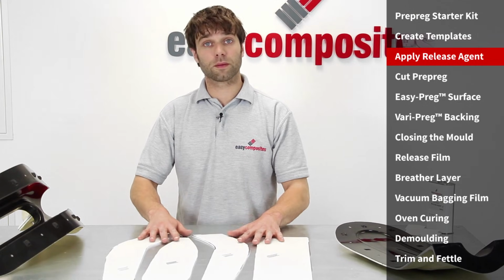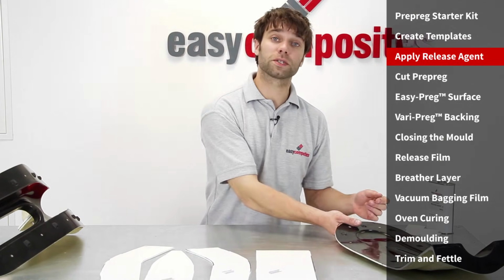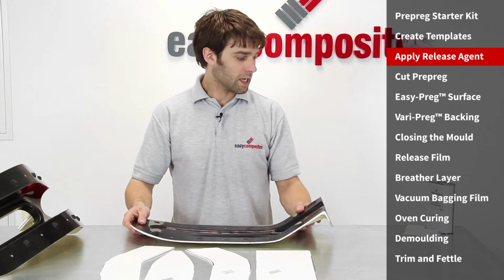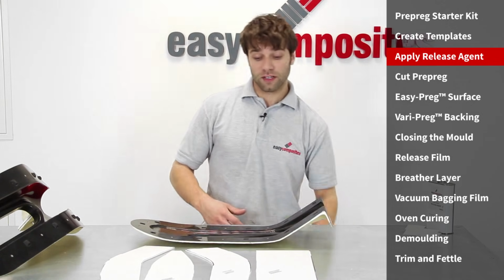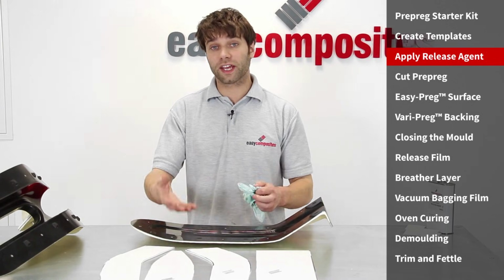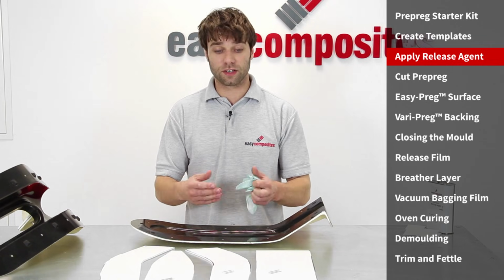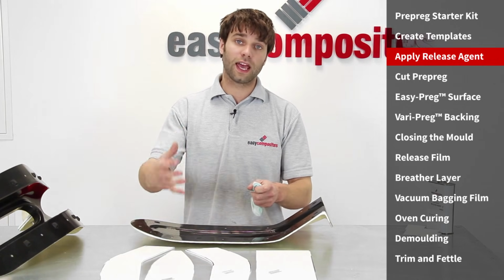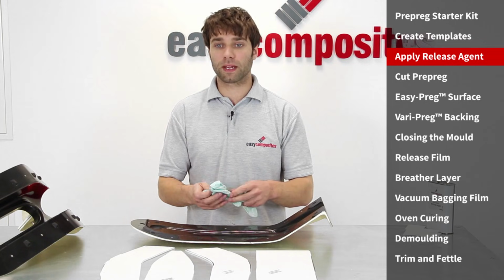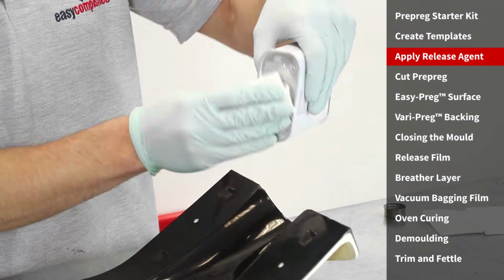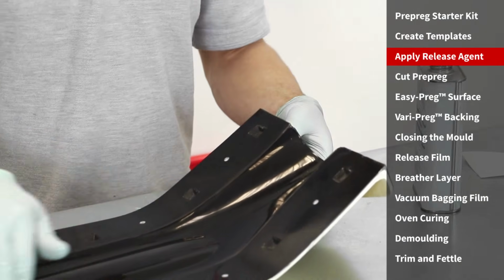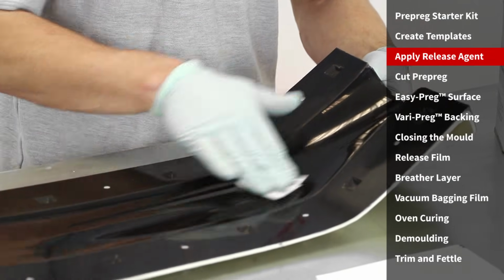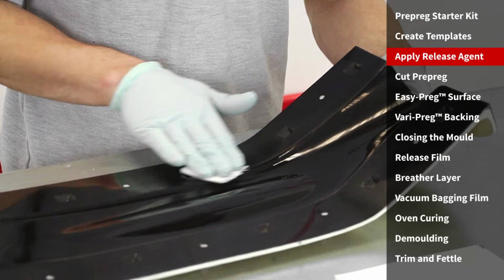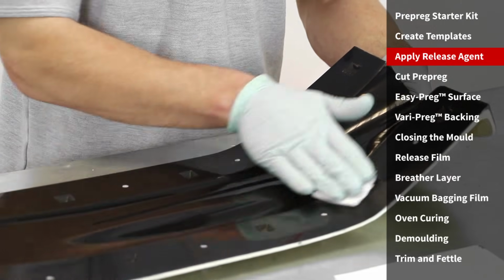Before we go on to cutting out the pre-preg material itself, we're going to take the opportunity to apply release agent to the mould. Now, as you may have already gathered, we've produced a part from this, so it's already had several applications of release agent, but it's always a good idea between every release to apply one more application. Conventional release agents such as wax and PVA don't work for pre-pregs because of the high temperatures that are involved, so you really have to use a chemical release agent such as Easy Release.